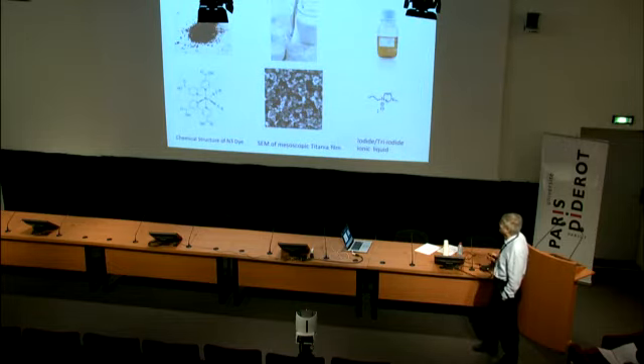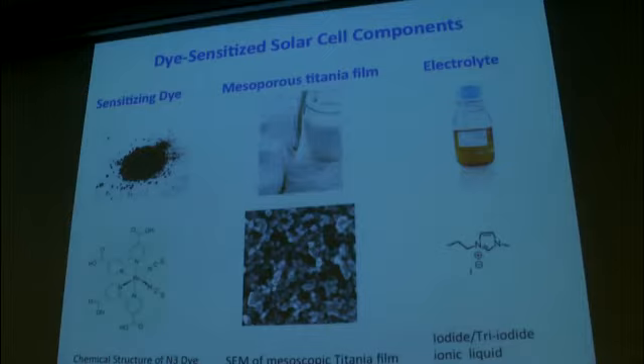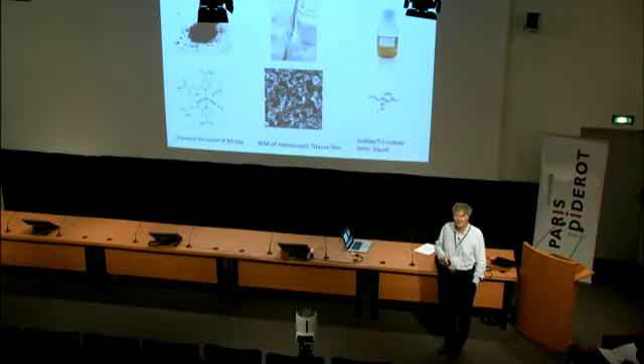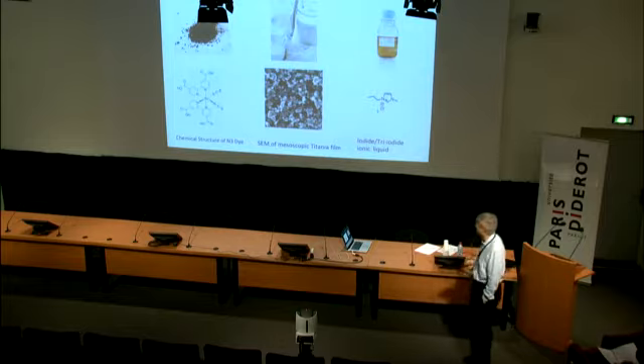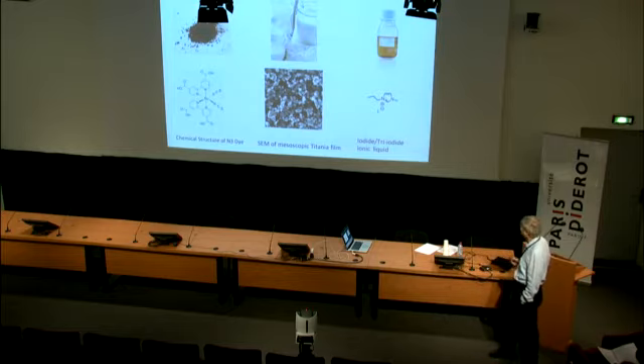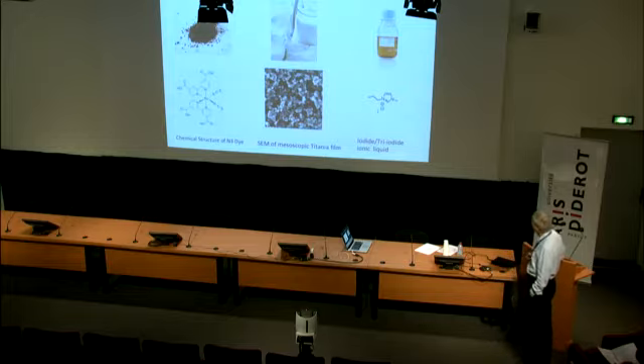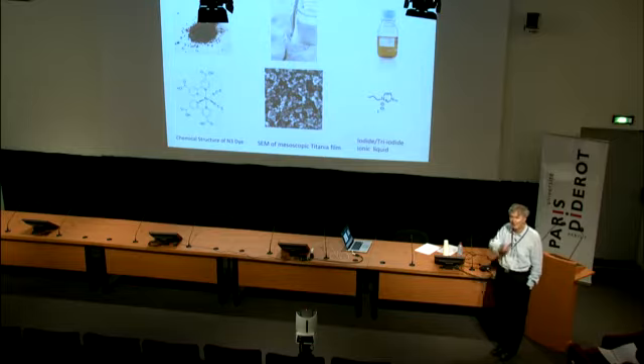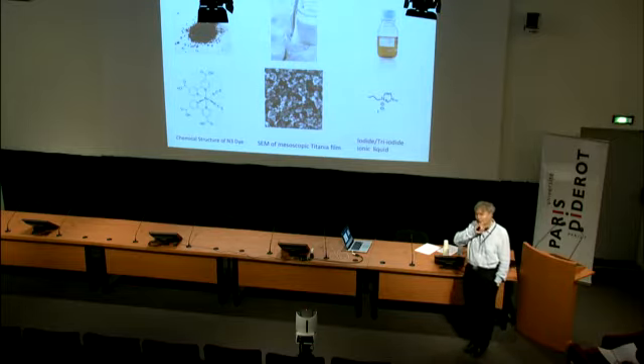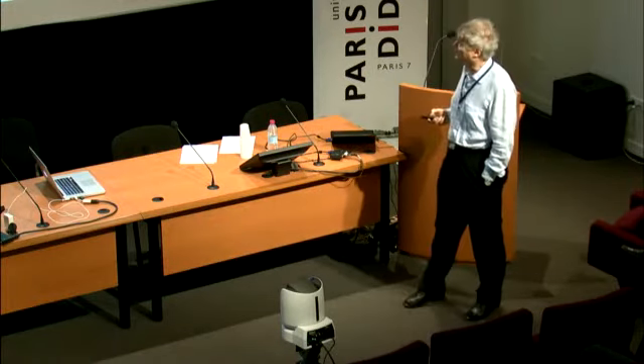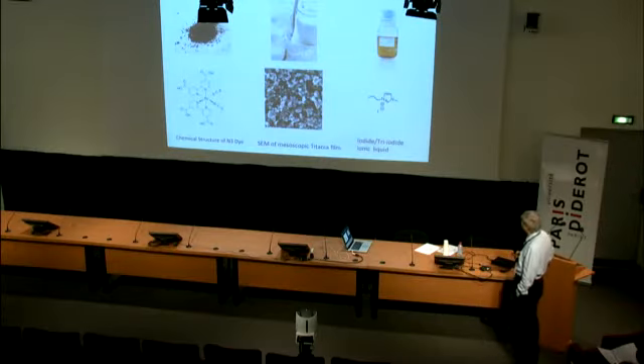So the components then of the sensitized cells are the dye. Here we have one structure, which is the ruthenium complex. Very recently, the ruthenium complexes have been beaten by organic dyes. So I saw it coming, but it has happened. I'll show you later which dye it is. And so we have the mesoscopic titanium dioxide film, and this is an ionic liquid. Industry likes to use ionic liquids as electrolytes because they have no vapor pressure and are easy to work with, and you can solidify those ionic liquids by just putting nanoparticles, silica nanoparticles, into the ionic liquid. So they're very, very important electrolytes.